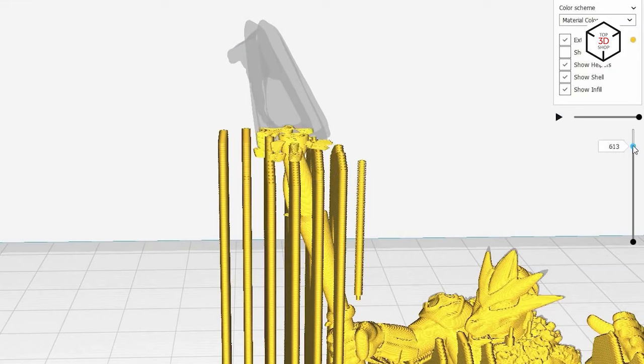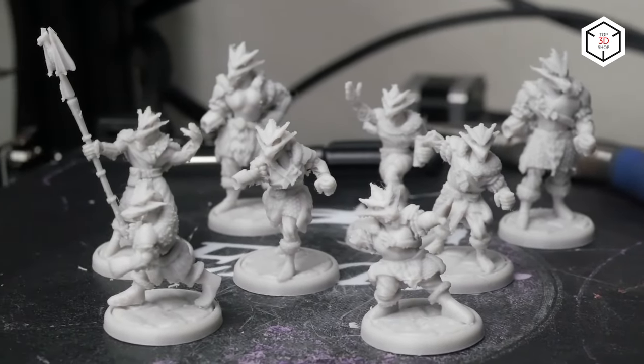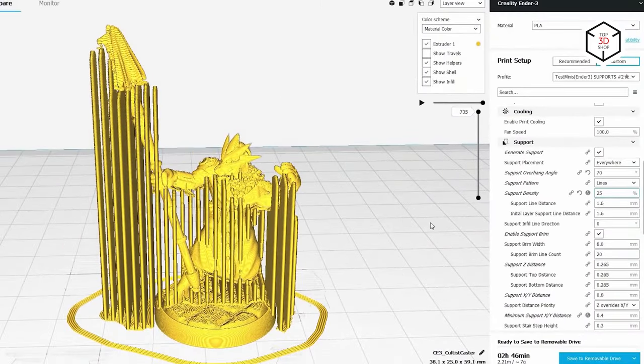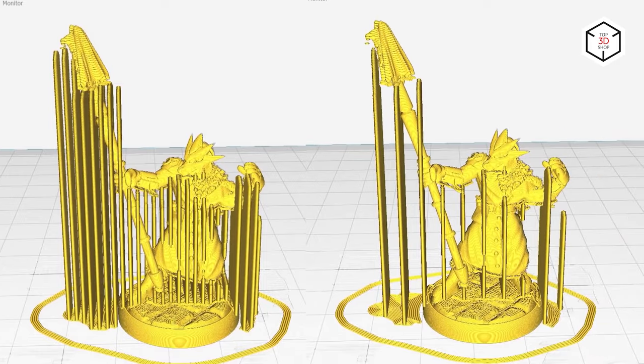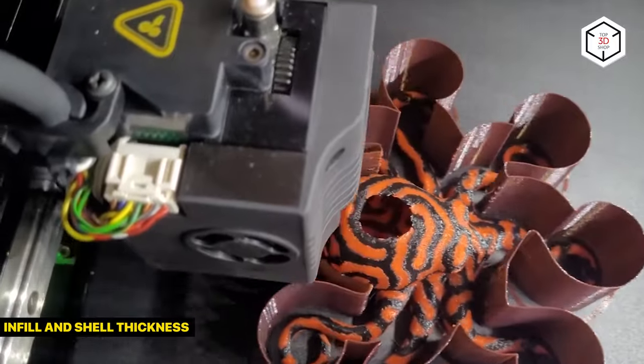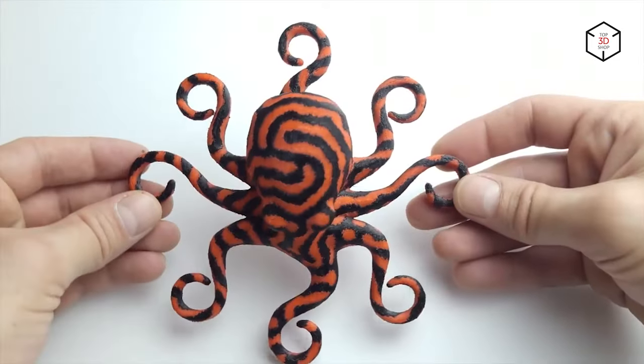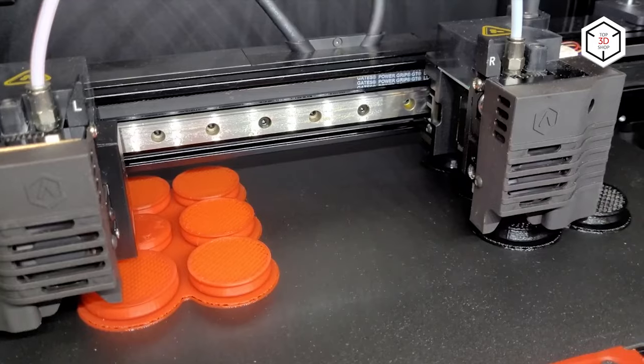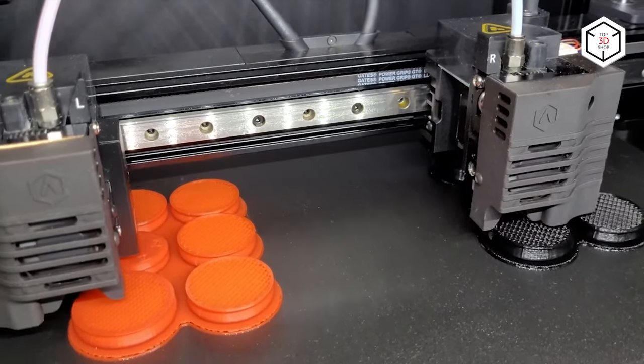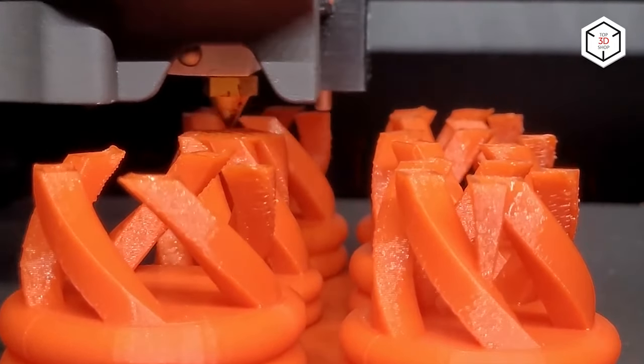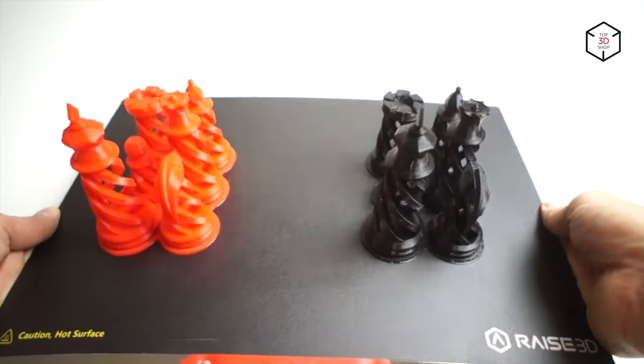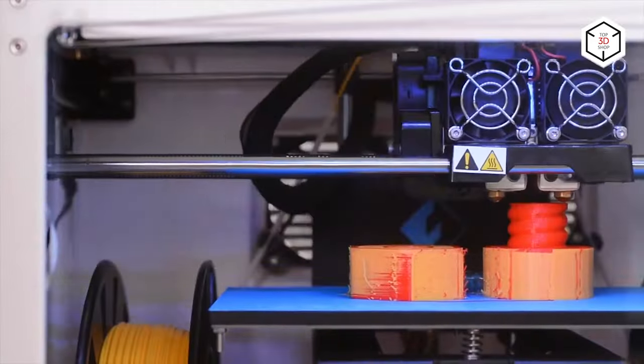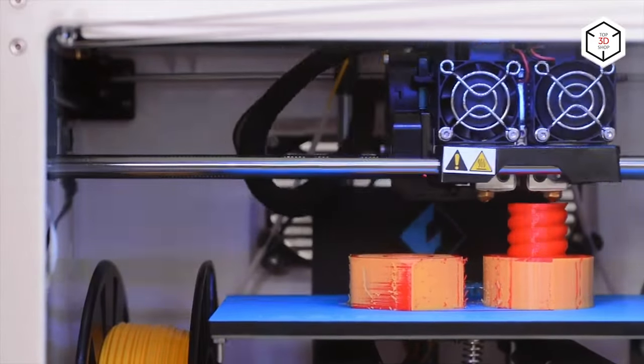Note that this usually requires a dual extruder 3D printer. Insoluble supports will naturally affect the model surface quality, so it is advised to minimize their use to a reasonable limit or devote sufficient time to post-processing. All FDM models have a certain peculiarity. They are often printed hollow to save on material and time. The external solid layer is known as the shell, while the internal structure with low density is called the infill. Both these parameters have a direct impact on the model's strength. For a desktop FDM 3D printer, the infill is customarily set to 25%. As for the shell thickness, one millimeter is enough to rapidly produce parts with decent characteristics.